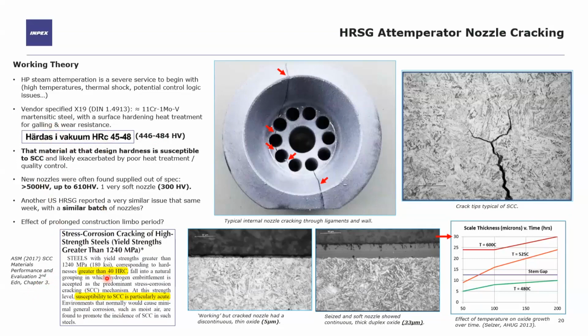And we've hardness tested on the bench and portable hardness tested, probably 15 nozzles now, some brand new, some cracked, some used but not cracked. And many of them are out of spec, up to 600 Vickers, with many above 500 Vickers. There was that one very soft nozzle, that's a special case. And when we contacted the US branch of this vendor, shortly after we mentioned it, they reported that another US HRSG had reported a very similar issue that same week. What's interesting there is that their manufacturing date was very similar to ours, so maybe there was a batch issue there. In any case, for us, the root cause is most likely selection of a cracking susceptible material exacerbated by poor heat treatment control.